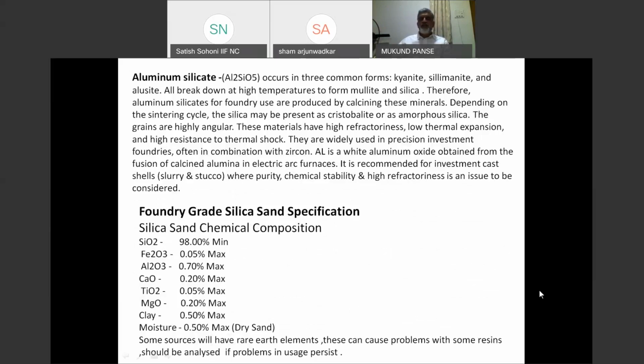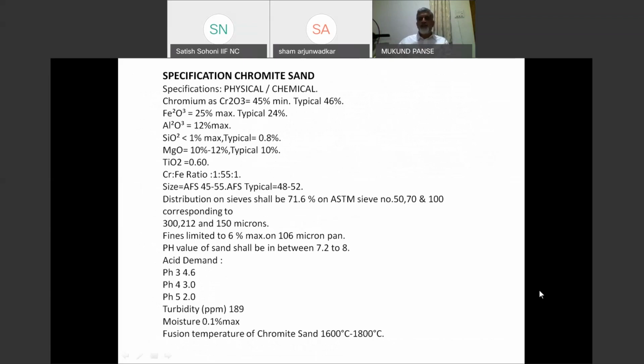The specific chemical specification of silica sand: it is 98% purity, and mostly you get this purity. However, you should control the TiO2, CaO in this, and also the clay percent and moisture. This is the specification of chromite sand. The chromite is around 45 to 50%. Iron is very high. You have to control the SiO2 percent. Now the specification mentions less than 1%. It is difficult to get 1%. But if it goes more than 3 to 4%, you will probably end up with problems. So you should check that. Also, the distribution you should check. You may not get the exact distribution you want.